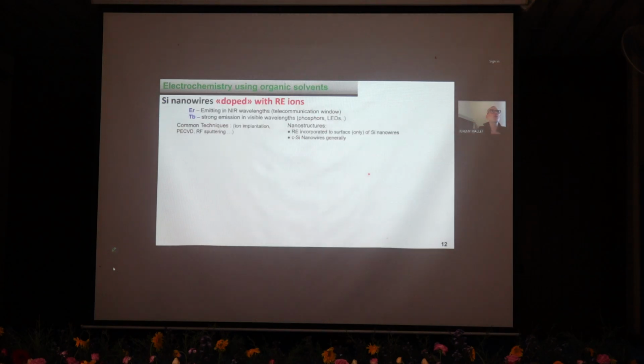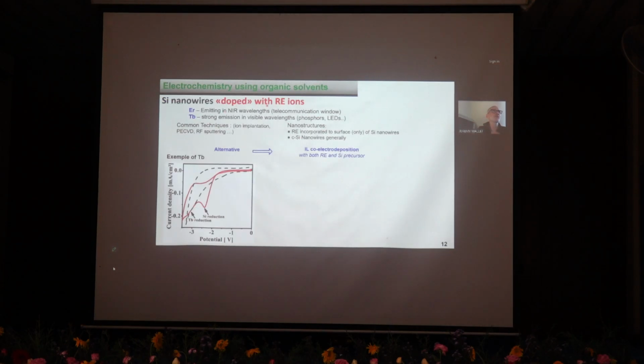We can also use, of course, silicon templates, for instance, use photoresist to grow the silicon, and after removing the photoresist, we have some silicon, for instance here silicon dots, which are submicronic dots. We can also cover, if the support is sufficiently conductive, silicon on top of nanostructures, nanocones, for instance. Here we have, by reactive ion etching, a morphology of crystalline silicon, and then we can grow silicon deposit on top. As I said, we can also, for instance, grow rare earths.